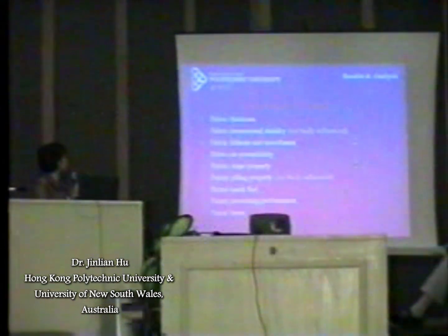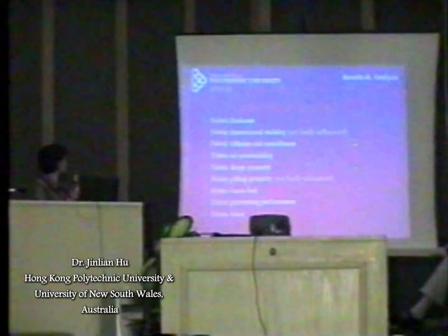Fabric thickness is increased. Fabric dimensional stability is not influenced, or it has very little change. Fabric fullness and smoothness are increased. Fabric hairiness is increased. Fabric thread property, the durability, is decreased. Fabric pilling property remains similar, and fabric harsh pilling is decreased.